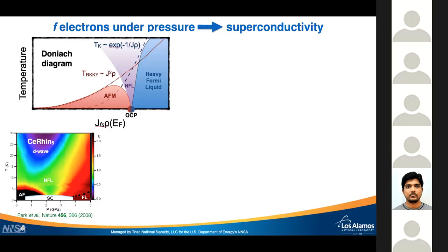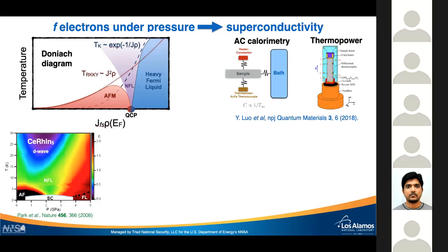So from the experimental point of view, we can investigate the systems under pressure using a variety of techniques. And here in our group, we use not only the standard electrical resistivity and Hall, but also AC calorimetry, which is really important, and we'll see this later on as well. When we have a superconducting state and we want to look for transitions that occur below the zero resistance onset. Another very nice recent development is thermopower measurements under pressure. That really allows us to investigate quantum criticality very well. And more recently, I have been very excited about thermal expansion under pressure.